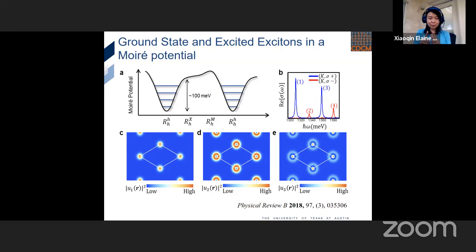They're actually a really enticing platform to pursue this, because for Dicke states to exist, you also want to have aligned dipoles, right? And these dipoles are already aligned to some degree, because if you think about the interlayer excitons, they have the electron and hole separated in different layers. They already have a preferred orientation for the dipoles. So I think this is a great platform to ask the type of question you're curious about.